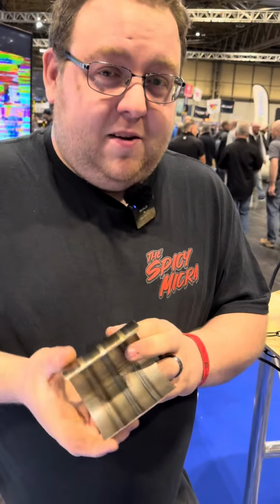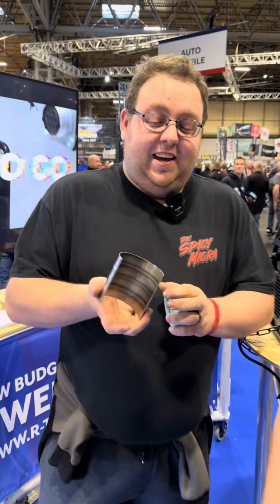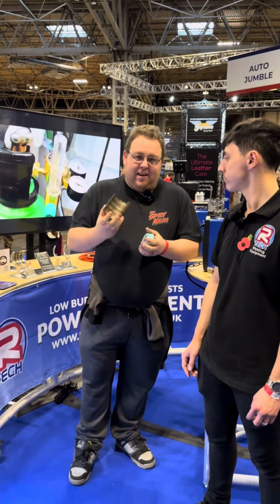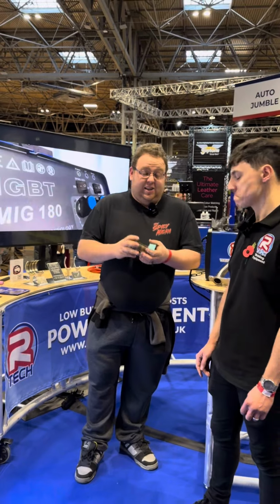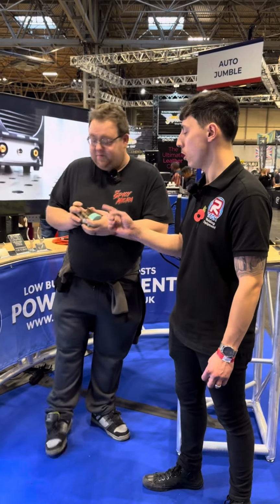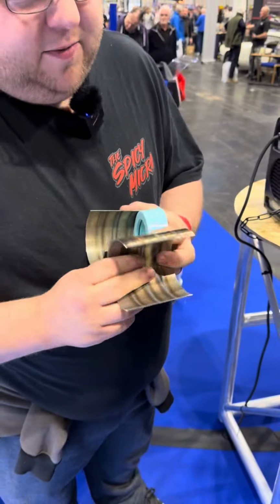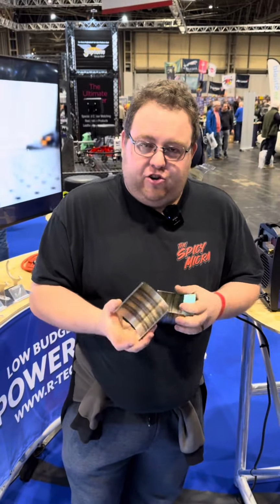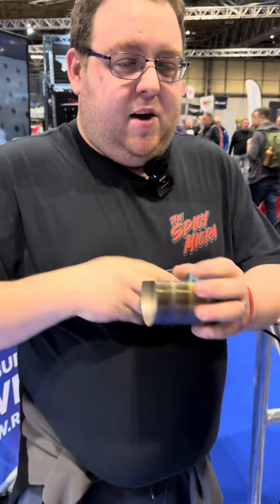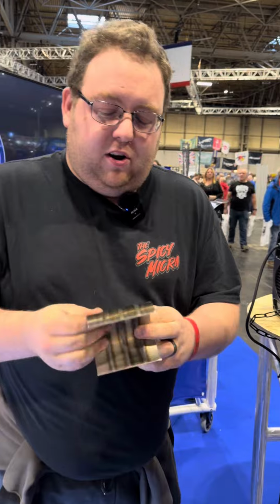If they look at you funny when you ask about purging, probably question their practices, because ultimately purging is going to give you the most reliability and the best product that they're going to be able to produce. And it's going to last a lifetime. Okay. And on the other one that's not purged, it's actually quite rough inside. Why is that? Yep, so this is oxidization. This is where the weld pool has reacted with oxygen. So as much as it looks like it's penetrating all the way through, you actually end up with sort of like a valley. So it's not actually fully welded all the way through.